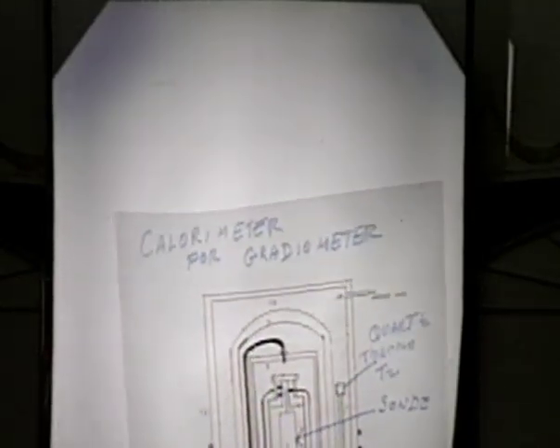So we could take this enclosure over here, and of course we needed to put power into the calorimeter in order to do the electrolytic cell. But what we were doing then was just to keep the heat flow, in other words, we kept the difference between the inside and outside temperature constant. The heat flow would be constant, so we could keep Q, the heat flow from the container containing the electrolytic cell to the outside world, constant, and just measure the power required to do this. And therefore, if we have an isolated black box with heat coming in, going out, and power coming in, we could measure the power balance, energy balance, and all that.